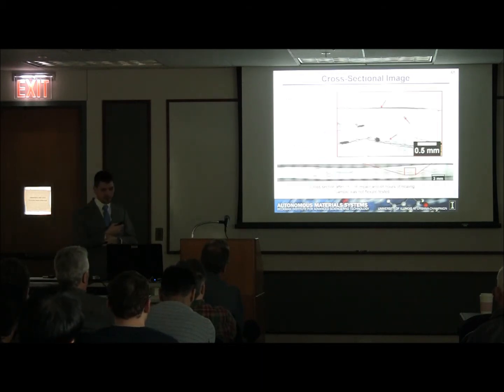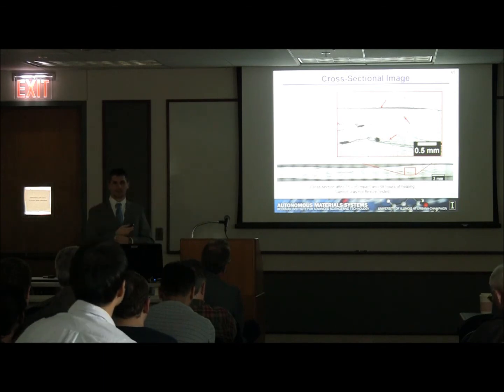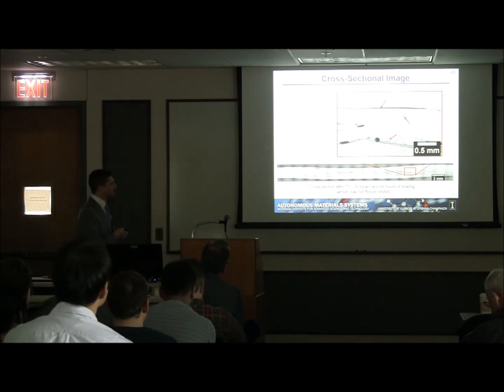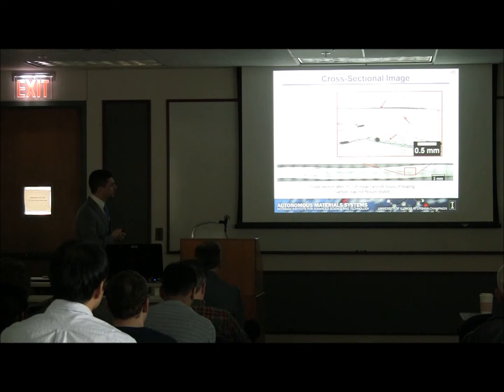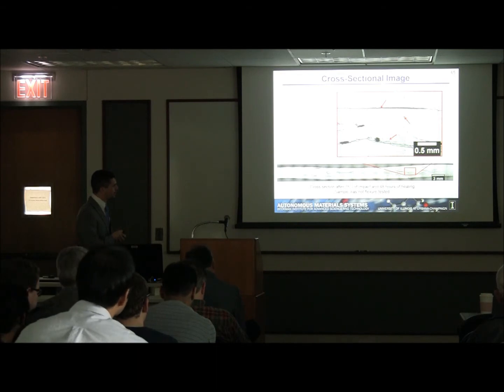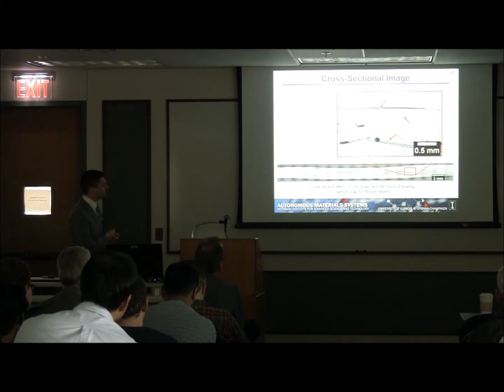We can take a look at cross sections of samples that have been impacted and filled with our healing agents. We can look for visual evidence of healed material inside of the crack. So we have the healed delamination here, healed delamination here. And interestingly, like I mentioned before, there are still regions that are unhealed. So we have this delamination here, which did not receive healing agent and was not healed.